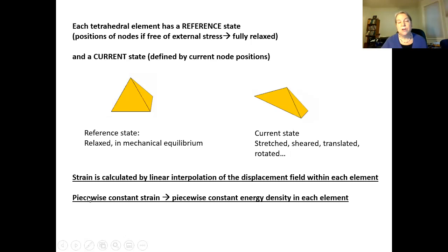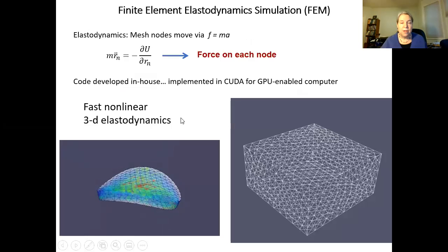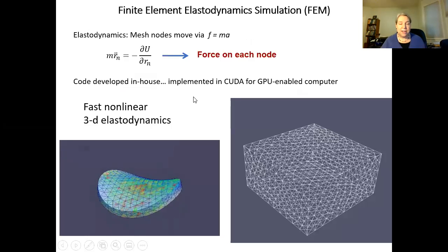And that means that we're assuming, again, this is a pretty naive, fundamental, basic formulation for the finite element. We're just treating the strain as if it's piecewise constant inside each element. So we don't have to worry about gradients of the strain. But of course, it'll be different in each element. So we can have gradients of the strain across the sample, but the strain is treated as piecewise constant within each little volume element.